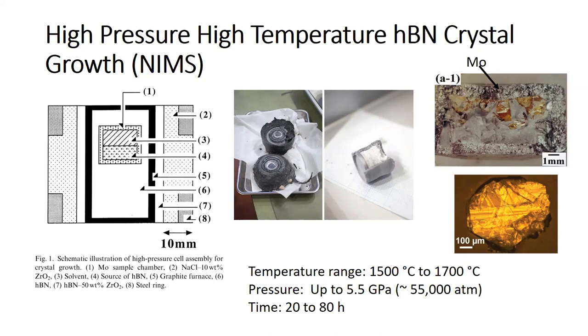What I contend is that this isn't... Yeah. What's the size of the sample that they, it's a millimeter. Okay, so it's a centimeter square. Yeah, so the crucible is probably a couple centimeters across. Well, I guess here we have scale there. Okay. And that's the challenge when you're operating at such huge pressures, it's difficult to scale this process up to very big. And it's also a difficult process for academics to duplicate because of the cost of the pressure.